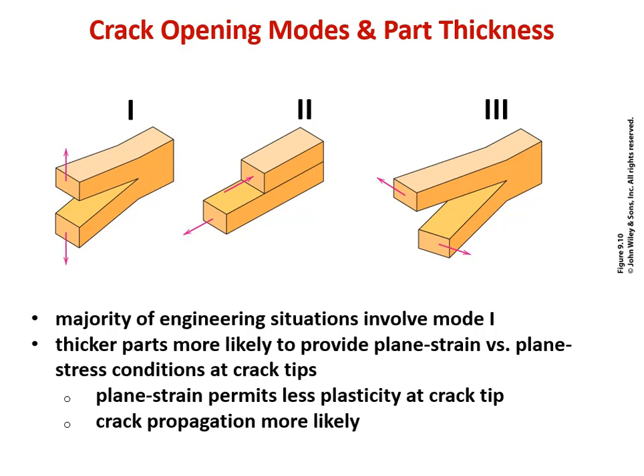So when we talk about crack opening modes and part thicknesses, and we're looking up fracture toughness benchmark data for a given material, we're going to look for a test that was done with mode 1 loading and that was done on a test sample in a plane strain condition. So mode 1 plane strain is going to be the most conservative condition, and if the test was performed that way, it's going to be bounding for almost any kind of similar temperature and environment condition that we would put that material in in the field. So there's the role of crack opening modes and part thickness with respect to test data.